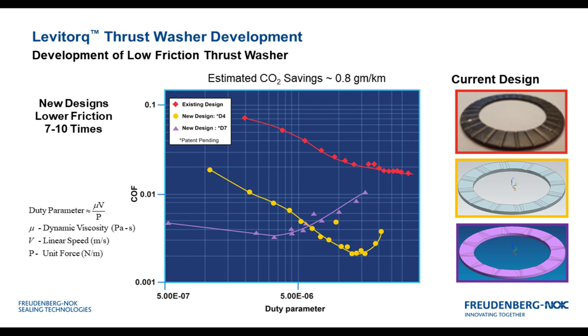When you're on the far left side, you're at a dry condition where you're not having much lubrication. As you move up in speed, you'll see that lubrication becomes greater and the friction will drop, and you can see that drop in the red line on the current design. If you can optimize friction, you can actually get to a point where you have no contact between the metal surfaces of the parts. That's when you go completely fluid dynamic.